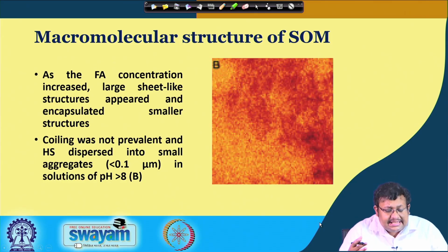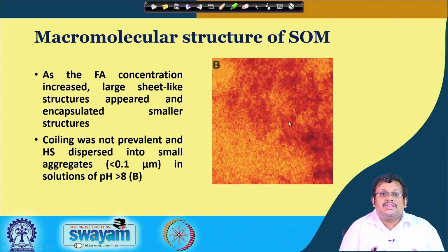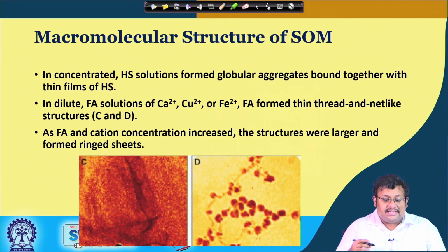As the fulvic acid concentration increased, large sheet-like structures, as you can see in this picture, appeared and encapsulated smaller structures, and coiling was not prevalent. Humus dispersed into small aggregates less than 0.1 micron in solutions of pH greater than 8. So, you can see how this structure is changing based on the pH as well as the concentration of humic acid and fulvic acid fractions.